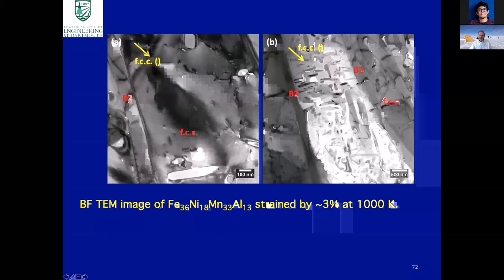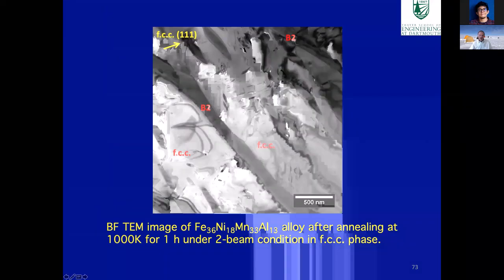One of the interesting things is when we test at high temperature, remember we had B2 lamellae and FCC lamellae. When we do the test at high temperature, we also get precipitation in the FCC phase, and these precipitates turn out to be B2 precipitates that are forming in the material, and you can see them again here. So this is a common feature of this alloy.